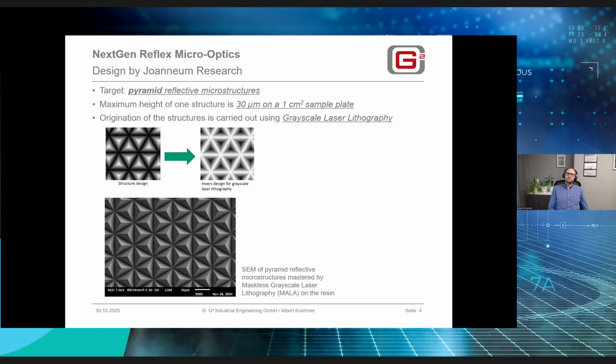The grayscale laser lithography, of course, uses a photosensitive resin, and the areas of the, let's say, the top of the pyramids and the bottom are exposed to a specific light dose on the substrate to get out the needed 30 micron height structures.